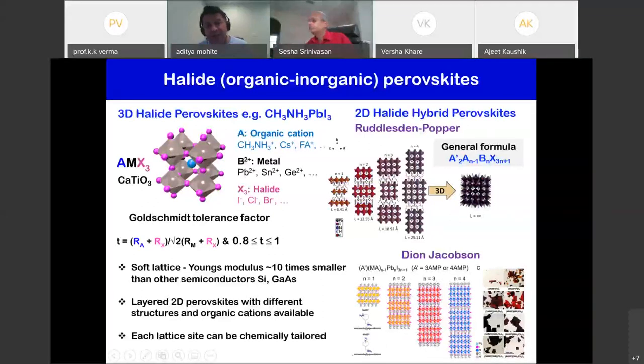You can very controllably tune the thickness of this layer, which we refer to as the N value. And so you can see here there are two slabs of the perovskite octahedra, and then there are three slabs, which is N3, four slabs, and of course, the infinity case is the three-dimensional one. And you can have other motifs of this, for example, Dion-Jacobson is another structural phase that's available.